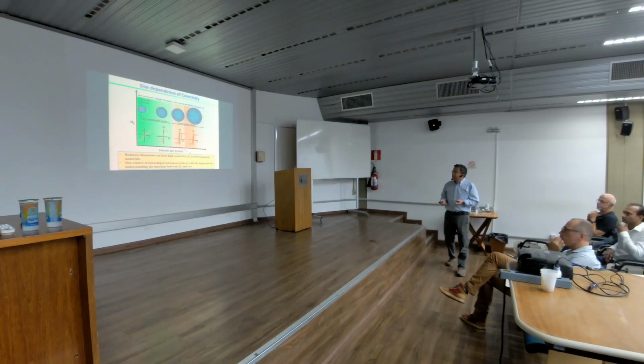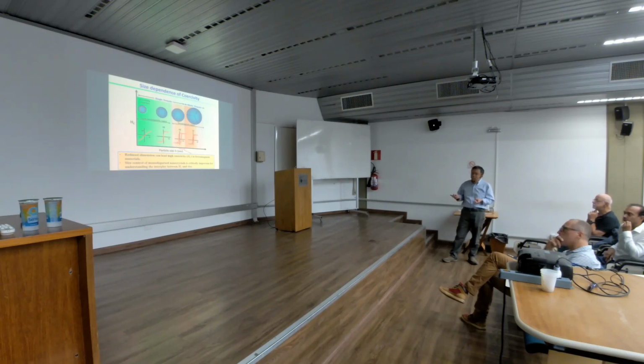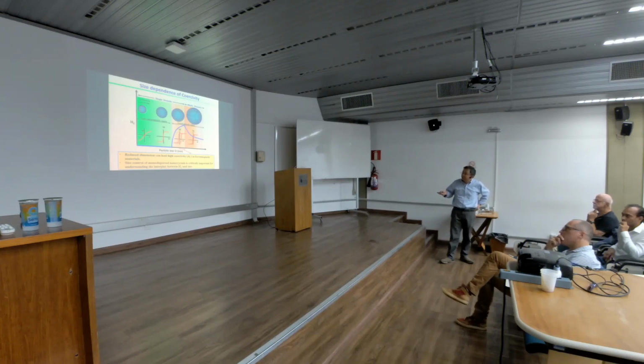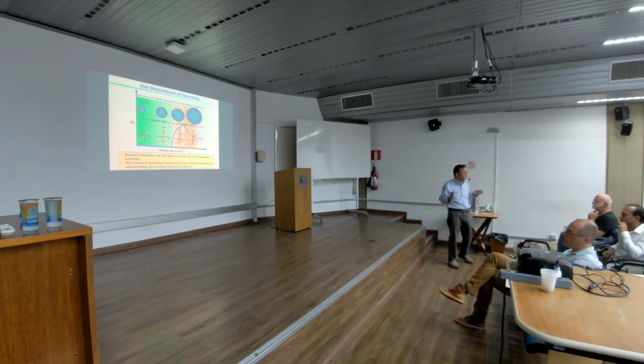Okay. But we already know for quite a while, when we dealt with micro-sized particles, when we make the ferromagnetic materials smaller, back 30 years ago, when I was young, we could reach micro size, but not nano size. We already realized that the coercivity, which is the main topic of this talk, can change with particle size. If you keep reducing the size, first it goes up and then goes down, reaching the peak when the particle size is called single domain size. What do you mean by single domain size? Each particle has only one magnetic domain. So that has been already known.